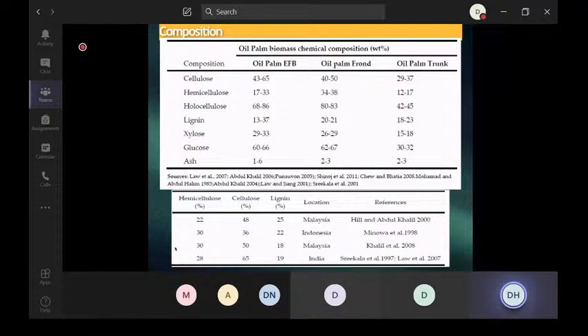Particularly, I'm talking about lignin. The lignin content in many bio-waste materials is extremely low. But in this one particular plant, oil palm, lignin content is nearly 20 to 21% for frond, then 18, 20, then 13, 13. So it's very high lignin content. This is so important when you are working on bio-waste material and making waste to wealth applications, where you are 100% sure that the lignin content in the bio-waste material is extremely high. If you don't have such high lignin content, you end up with nanoparticles, but they are not useful for very high-end applications.